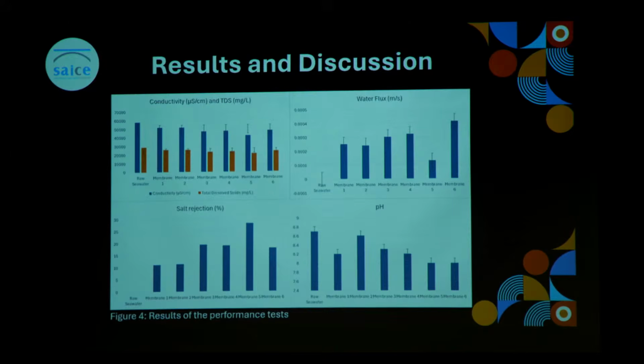The standout performer from this study was membrane 5. It showed the highest salt rejection rate of 28.15% while reducing the conductivity to just above 30,000 and reducing the total dissolved solids to just above 21,000. This suggests that membrane 5 is the most effective amongst all the membranes that were tested. However, this peak in selectivity comes at a cost as it has the lowest water flux of all the observed membranes.